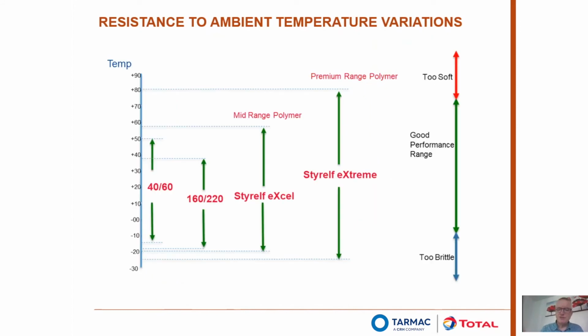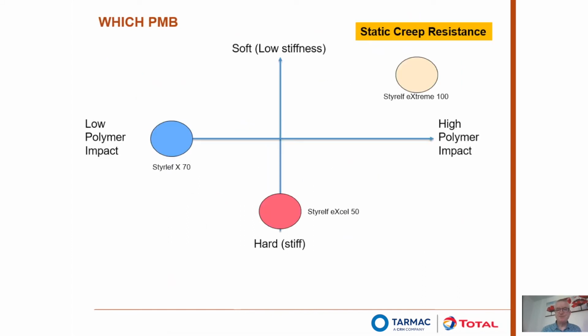What that translates to in terms of temperature is performance. You can see with Styrelf eXtreme over a much wider temperature range, somewhere between sort of 80 down to -20, -25 degrees C, compared with a 40/60 that's probably sort of -12 up to about 50 degrees C. So this is the impact. The mid-range one you can see around about +60-ish down to about -20. So again, mid-range polymers are starting to give significant improvement, but the extreme, the high polymeric impact gives a really good protection against ranges of temperature.